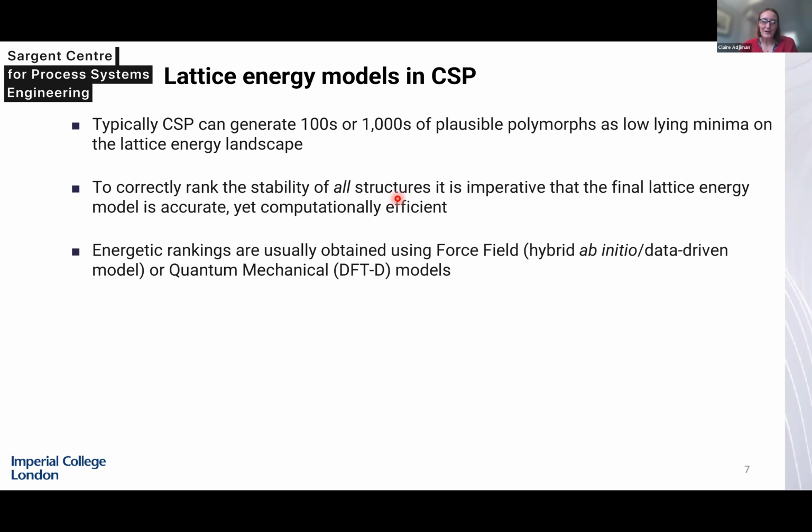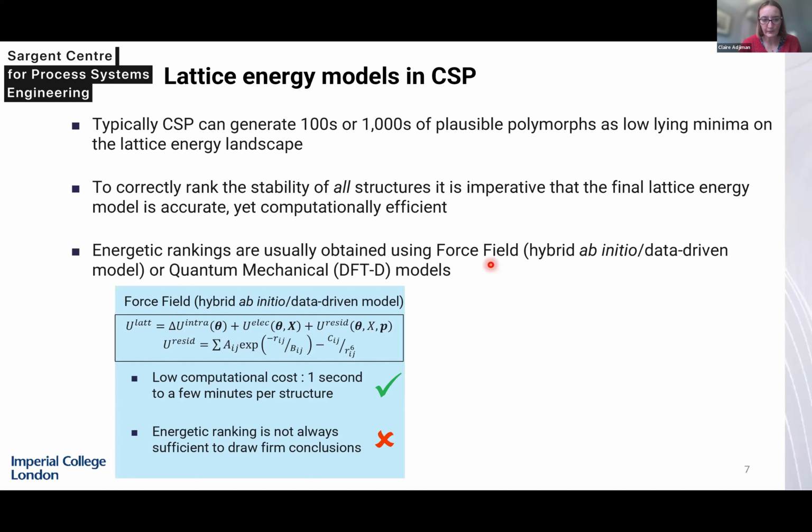Unfortunately, because the atoms are quite close together, we can't get away with too many approximations here. So to get a sufficiently accurate ranking for applications, we really need to use quantum mechanical methods that take into account the whole of a periodic structure, essentially to infinity. These, as you might imagine, are quite expensive to compute. And so what we're going to try and do is to develop some initial models that are like force field models that are a bit less expensive and enable us to screen through potential structures to narrow in on the most likely ones and do the expensive calculations only on those.